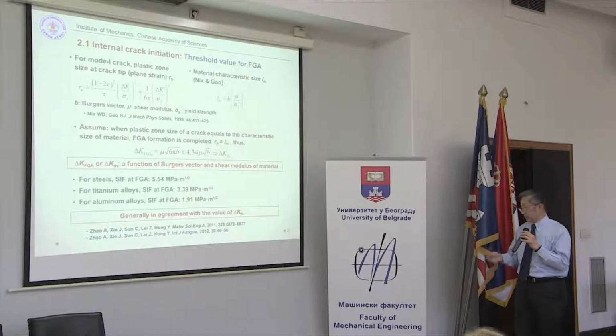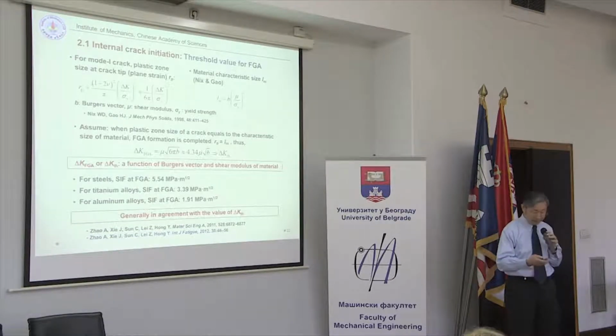And we may get the results for steels, for titanium alloy, for aluminum alloys. Such values are quite in good agreement with experiments.